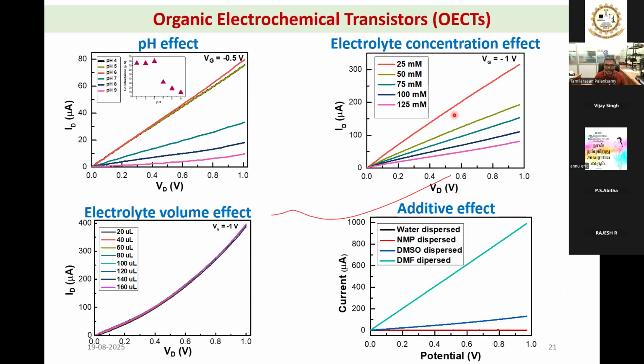Now we wanted to test its capability to use for biosensor. Still, it is not a biosensor. We are just trying to test its capabilities for different scenarios. For instance, in case I change the pH, what happens? At less than 6 pH, it is stable, but when you increase the pH to a higher one, say 7 or so, the conductivity drops. But remember our physiological pH is 7.35, so 7.34. So we should be working somewhere in this region.